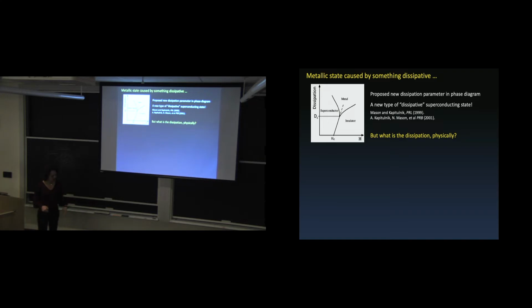And so we wrote some papers on it, and we proposed that the metallic state was caused by some dissipation in the system. So we came up with a phase diagram, and the phase diagram said that there's a superconductor on one side and an insulator on the other, and then as you add dissipation, you get a metal.